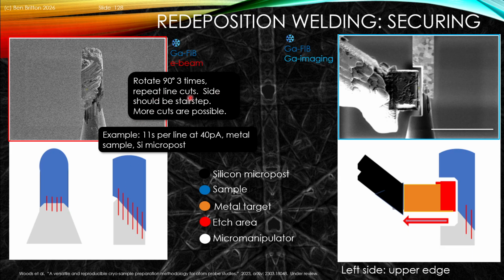So you do the repeat line cuts, and then more cuts to put in this, and then you get metal and there's posts reattaching to lock these two together. And that can be very useful, so that avoids you having to use the GIS to enable this deposition, so you can do it at cryogenic temperatures in here. The full description of this can be found in the paper by Eric Woods for this, and this is done for an icy sample in this case. The article is currently under review, but there's an archive preprint.